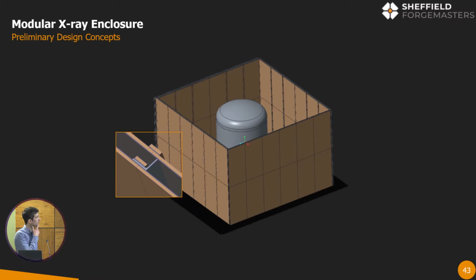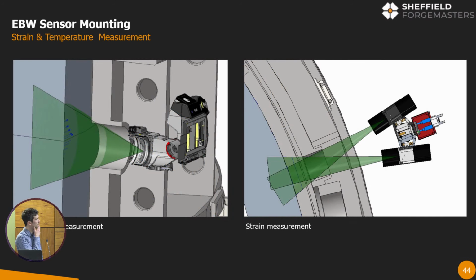And we're also looking at integration of various sensors onto the local welding jacket to provide validation data for our finite element models that we're developing, as well as providing process control feedback loops. So that includes temperature measurement during welding, strain measurement during welding. We're also again working with TWI to integrate UT testing on the welder as well. So if we do start to see the process drifting, we can either stop or potentially rectify what's going on.